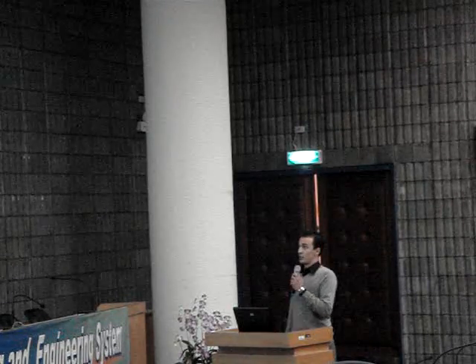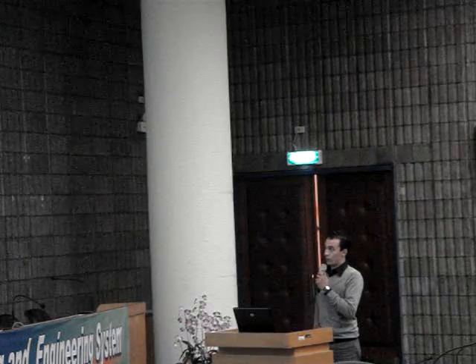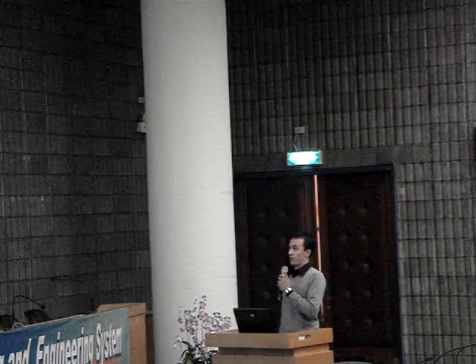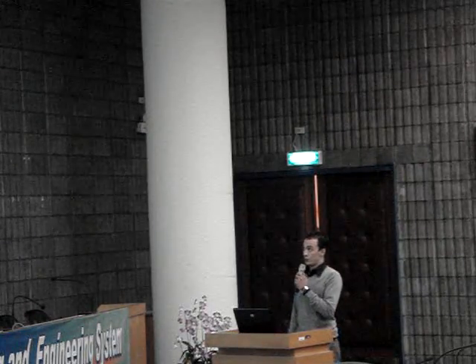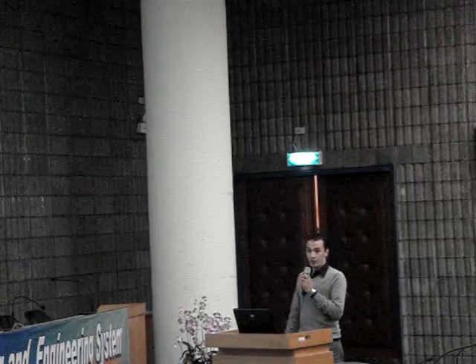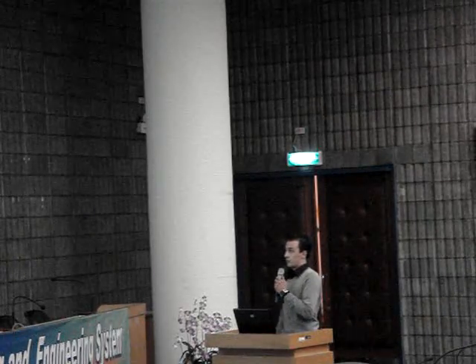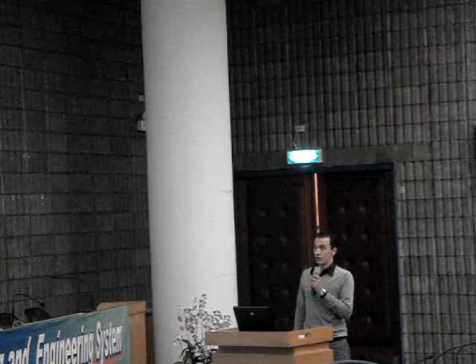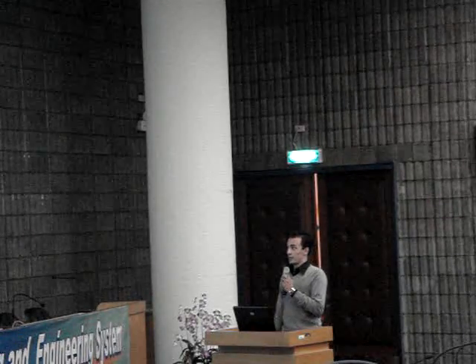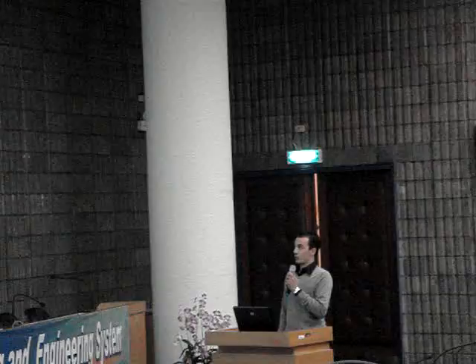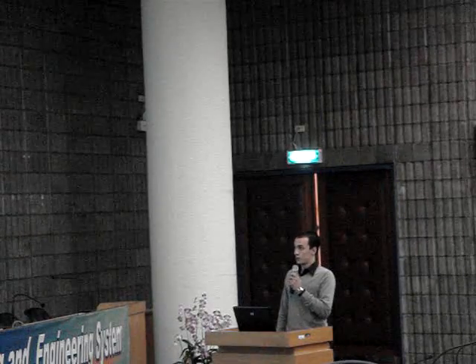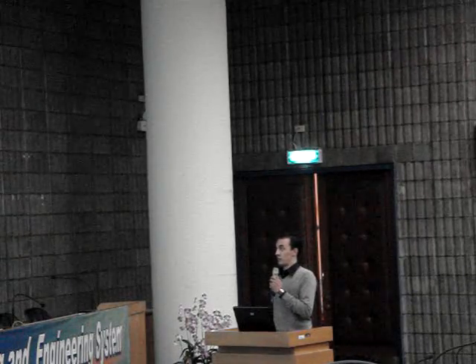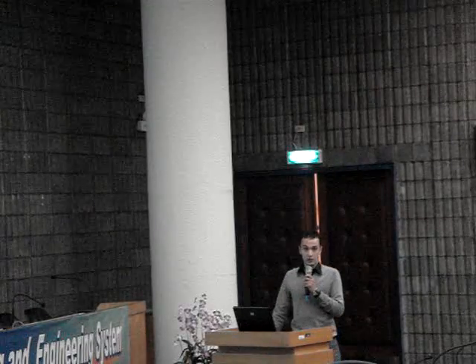To summarize my presentation: the SnBi metal alloy, with its low melting point and small thermal shrink, was used as the spraying material. We apply an electrically heated device and a high pressure hose pump to melt the SnBi alloy, pass it through a small spray nozzle, and atomize it into semi-molten small particles.